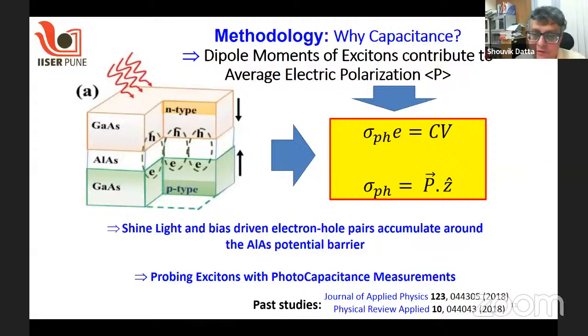Just to give you a flavor, in a more simplistic structure of a single-barrier sample, where there is only an aluminum arsenide potential barrier in the middle, we try to measure capacitance. And by measuring capacitance, we try to see the average electric polarization of all these dipole moments of